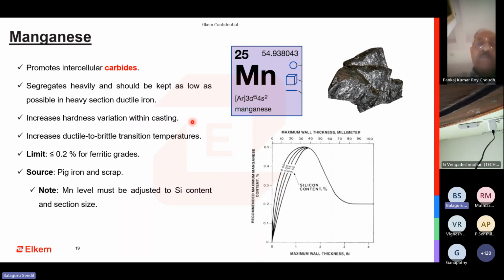Manganese must also be adjusted with respect to the silicon content. If you look at the maximum wall thickness here, if I want to have a 10 mm casting and my silicon is 2.5, then I should have a manganese in this range. But for the same thing, if I increase the silicon percentage, I can tolerate more manganese. So this tolerance has to be worked out: how much manganese can be tolerated with respect to the silicon content.